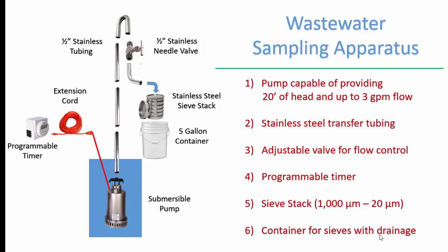Now, if you're doing influent, you're probably going to have a lot of debris and cellulose material, lots of toilet paper in influent, and they'll tend to clog up the sieve stack. And so we use a stacked set of sieves so that we can pull out particular fractions, a 300 micron fraction, a 100 micron fraction. If you're going over 3 gallons a minute, depending on how dirty the influent is, you can quickly overwhelm those sieves. So having flow control over the volume is definitely necessary. We chose stainless steel transfer tubing for everything. We didn't want nylon, PTFE, or any type of materials that could possibly add contaminants to our sample and be miscounted.